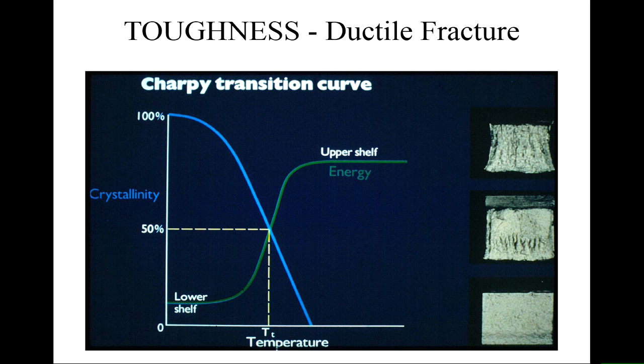So we have again a lower shelf energy and an upper shelf energy associated with the transition from brittle behaviour at low temperature to ductile behaviour at high temperature. So rather, in a Charpy test, than looking at the surface and just saying there's 20% brittle and 80% ductile, you now have an energy from that system, and that energy can be plotted directly on a curve, so there's a number that you can compare. And it's a little bit less subjective, therefore, than the drop weight tear test.